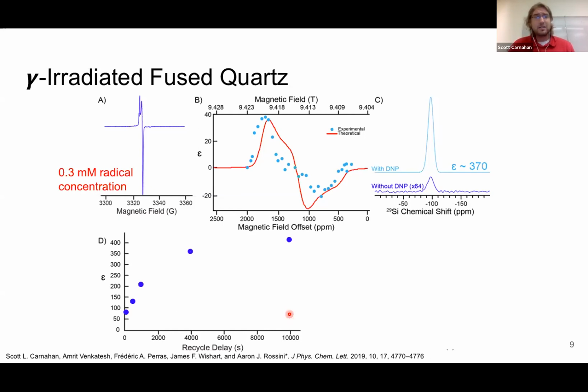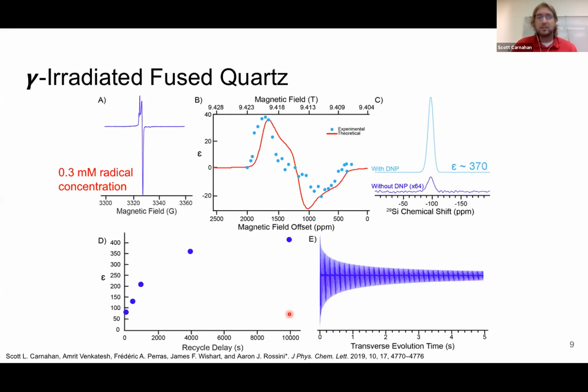Well, it kind of seems like a long time. Like I said, quartz has some special properties, with really long delays or relaxation properties. One of which is that the refocused T2, or the T2 prime, when I do CPMG acquisition, I'm actually able to acquire echo packets out for an entire 20 seconds, which is limited not by the sample system, but actually by the Bruker software. You can only acquire for about 21 seconds. So I'd be really interested to see how far out we can actually acquire things in the time domain here.